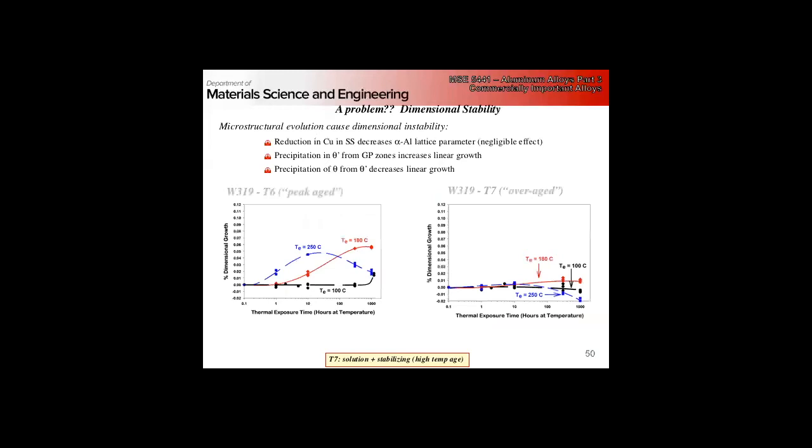Sorry, what's the parameter of dimensional stability? How do you define that? It's just linear. It's equivalent to thermal expansion, except it's not thermal. It's just how much longer has this gotten. And so it's not huge. At its peak, it's 0.05%.